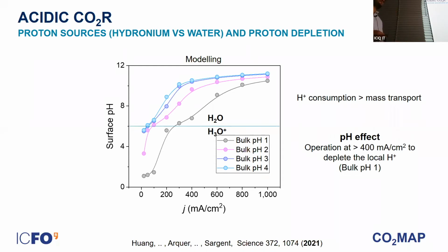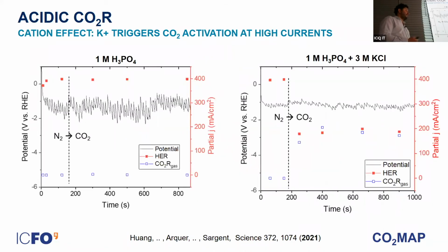This is a regime where you start getting the protons not from hydronium, but from water itself. So it's kind of at the threshold where the kinetic competition between generating hydrogen or CO2 reduction could be somewhere where CO2 reduction could win. You don't have so many protons that you can only make hydrogen; you have to get these protons from water too. But unluckily, at these conditions, almost nothing happens. Even if you operate at a higher current density, you can barely do anything but hydrogen.